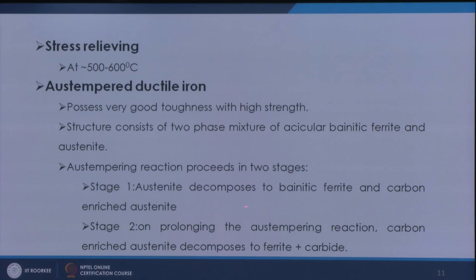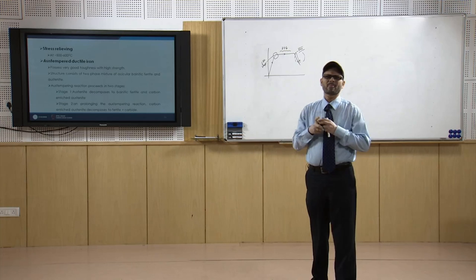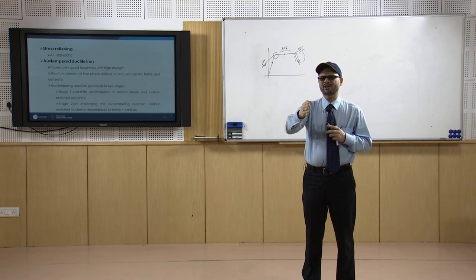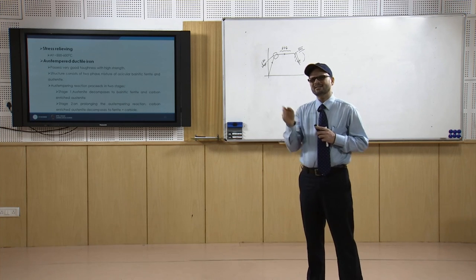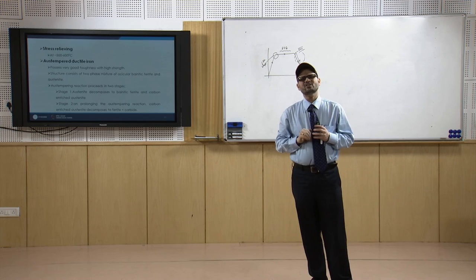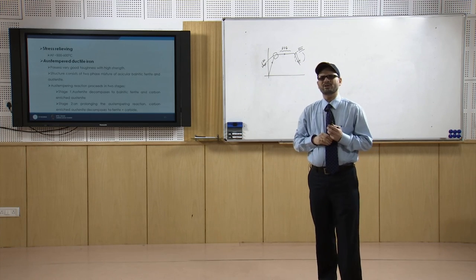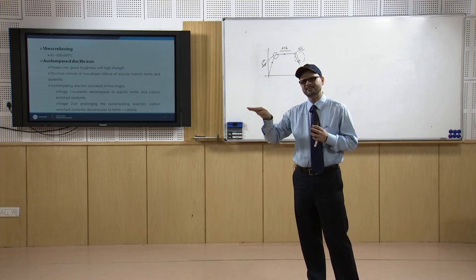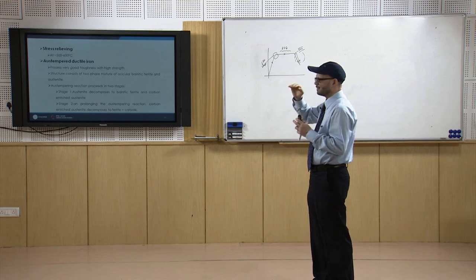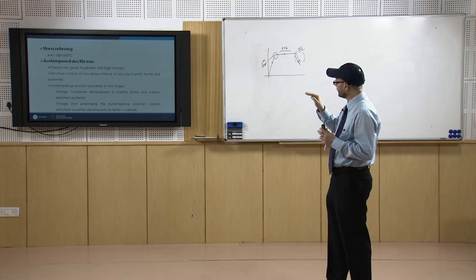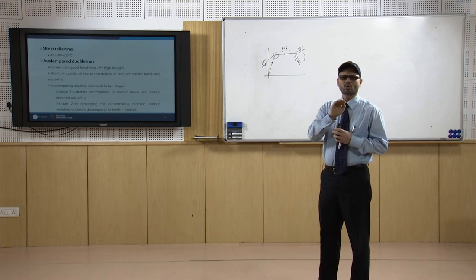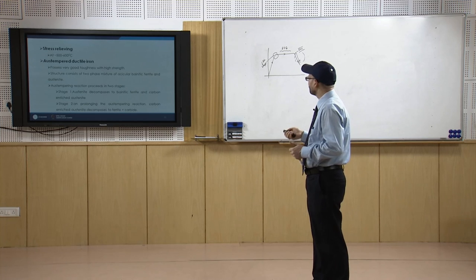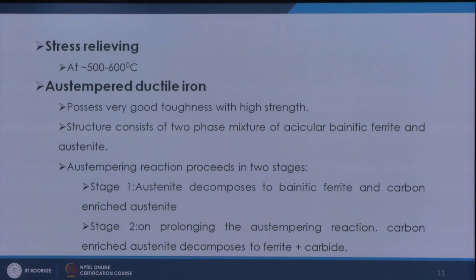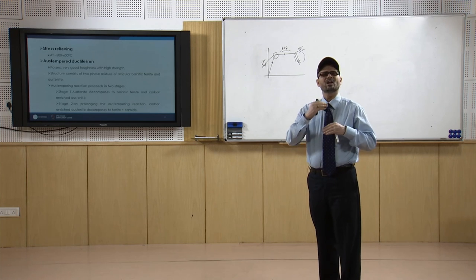Its structure consists of a two-phase mixture of acicular bainitic ferrite and austenite. As we have seen, in the austempering treatment, we cool down below the nose of the C curve and then hold, so that we get the bainitic structure. The same thing is followed here. We cool fast, but hold at a temperature of about 300 to 400 degrees centigrade, just below the nose of the C curve. That holding gives an acicular bainitic ferritic structure and austenite, which gives a large amount of toughness and very good strength.